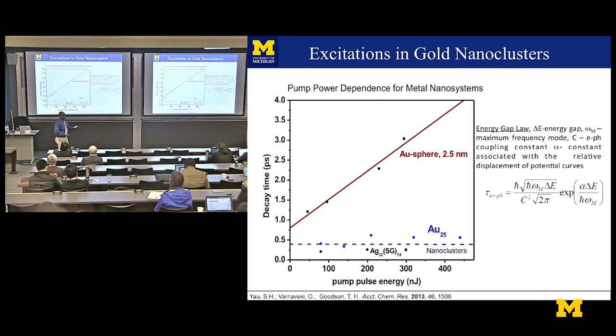At this point, we didn't even know. Okay, and so here's the electron phonon relaxation time, and here's the maximum frequency of the coupling constant. And here's the actual band gap. It says if you use a band gap proportional to the absorption of one of those peaks in the gold 25 cluster, you could actually model this using this kind of approach, the so-called energy gap law. Interesting. But we weren't done yet.